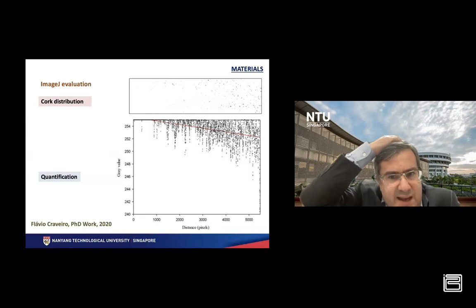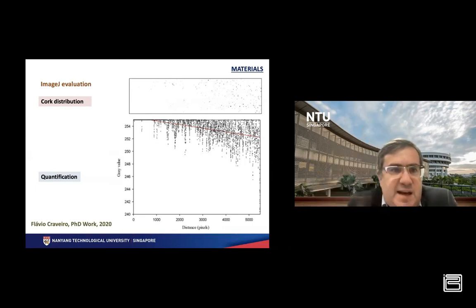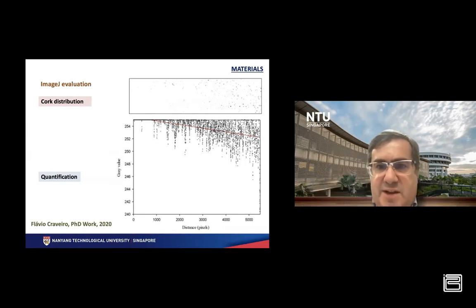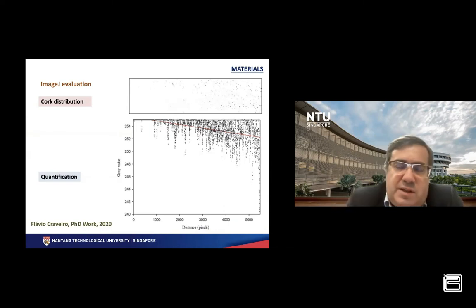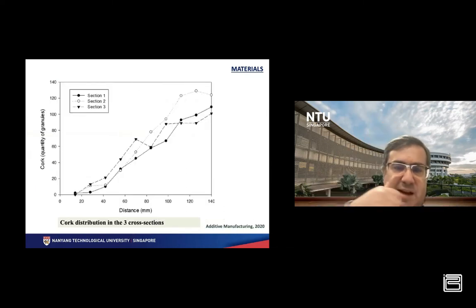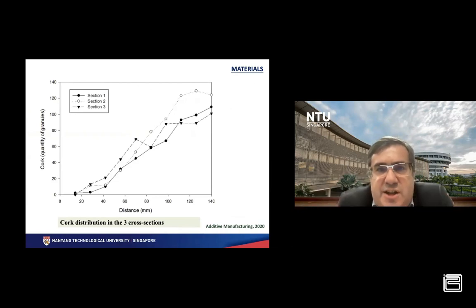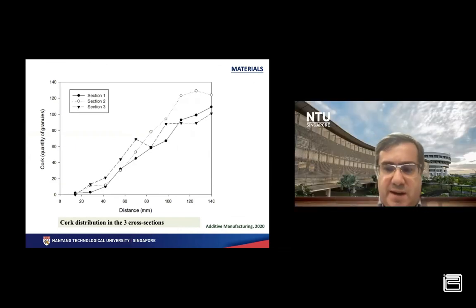This is an ImageJ analysis showing the cork distribution. And as you can see with our new printing head, it was possible to have a very good control over the distribution of cork along the printed structure. And again, we considered different sections, and as you can see, again, very well defined distribution of cork